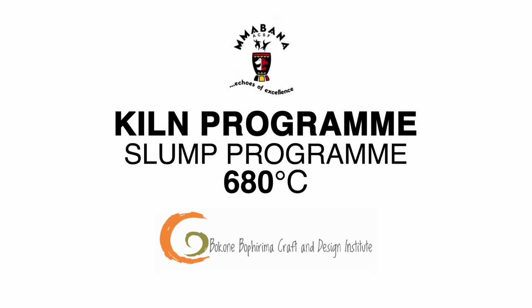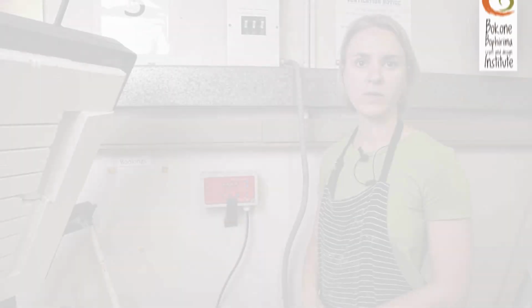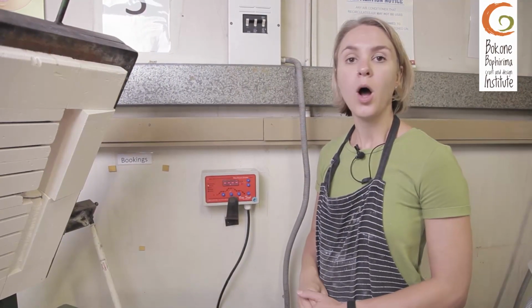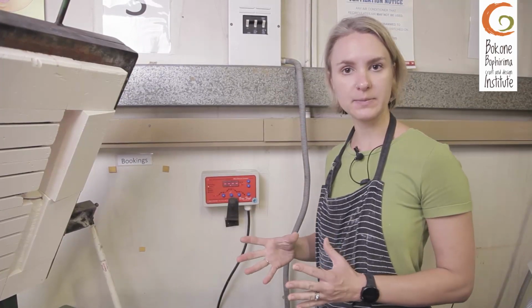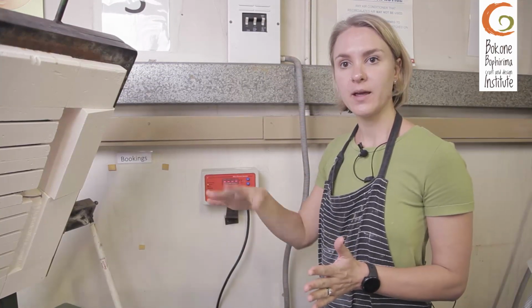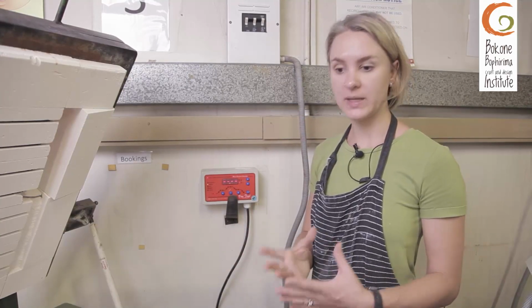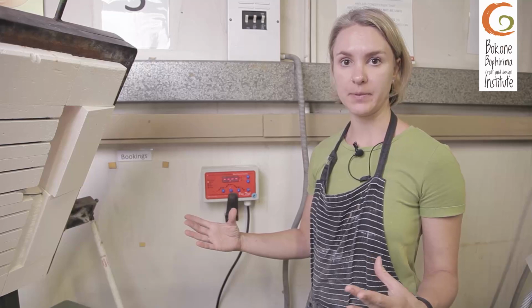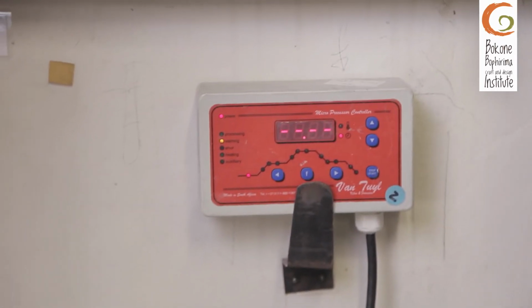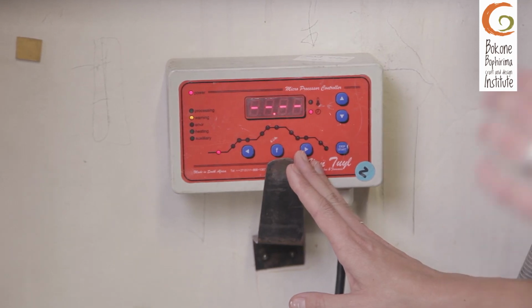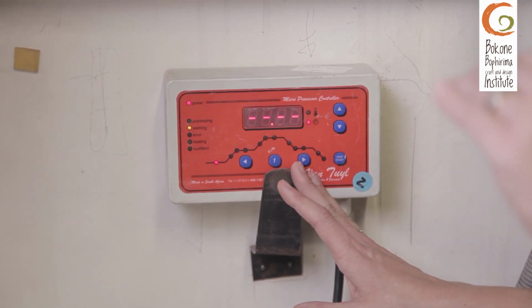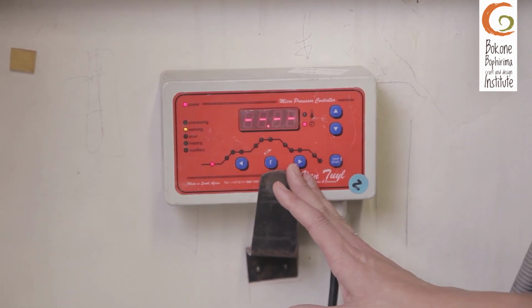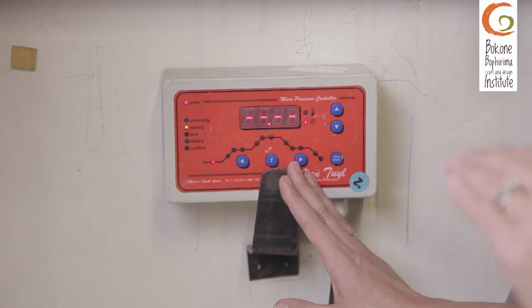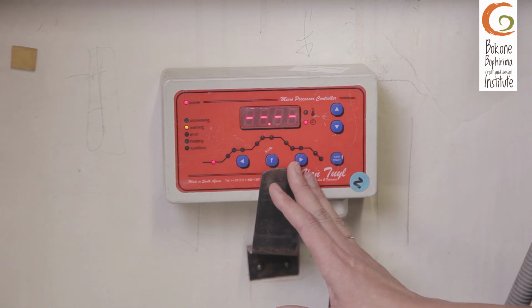Now I'm going to explain to you the process of slumping. And this is now especially for Connie's piece, where she's going to be slumping over the mold we created, or Lebel's piece where we are slumping into that plate shape. What is important to remember when we are slumping is that the thicker your glass is, the more weight it has behind it, so the quicker it's going to drop into the mold. So when slumping, it is nice to work with at least between a 6 to an 8 mm glass to ensure that you get that lovely desired shape that you want at the bottom of the surface.